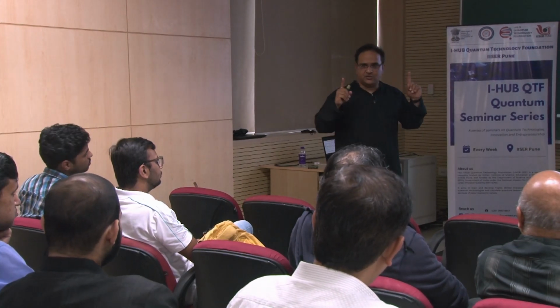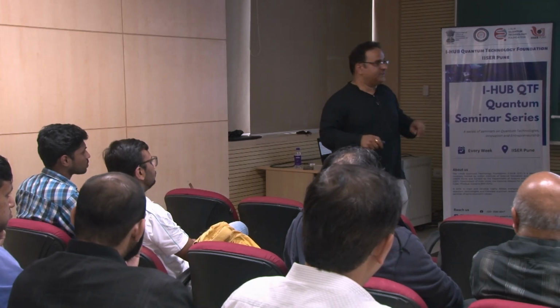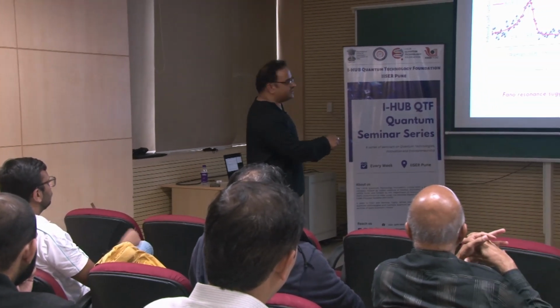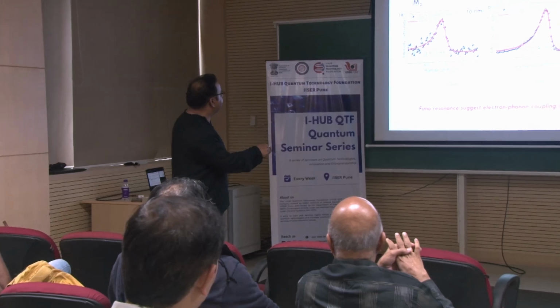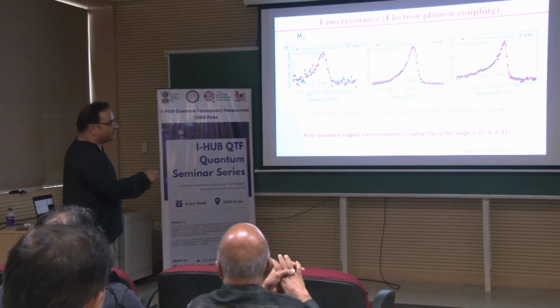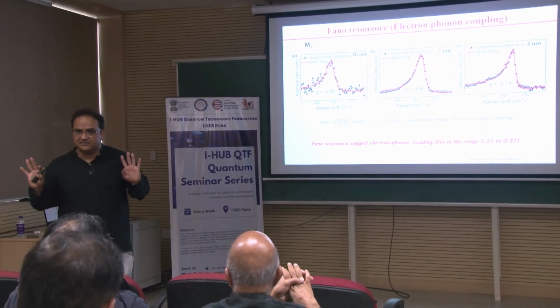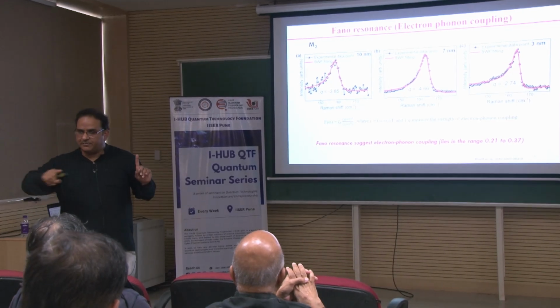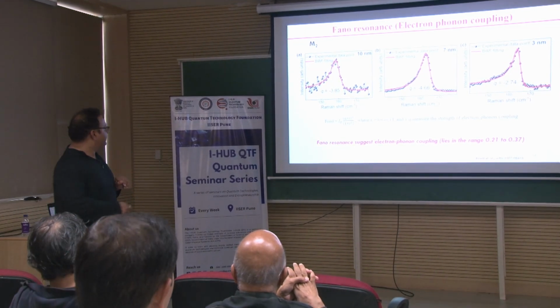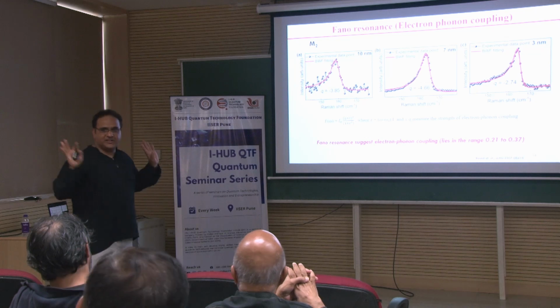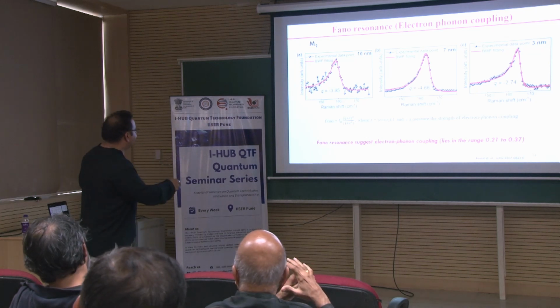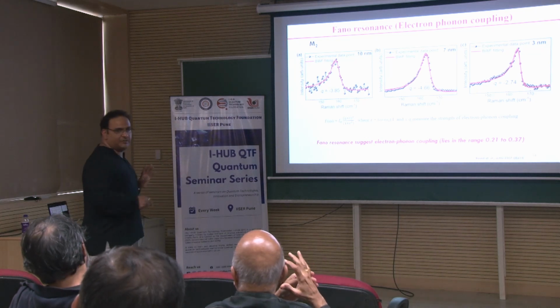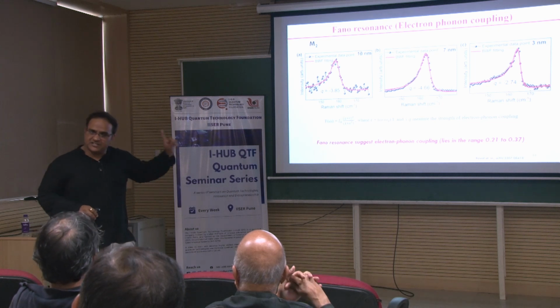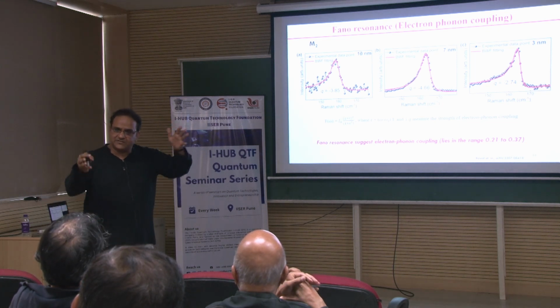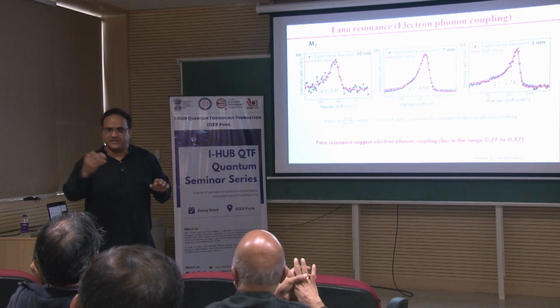So now here there are two parameters. In the earlier case, I don't know what the shape is. I just know this point as a function of temperature. It's a temperature dependent behavior. Here, I don't know the temperature. I just know the shape of this Raman peak. So this is a shape analysis from the Raman. That was just the temperature dependence of the frequency.